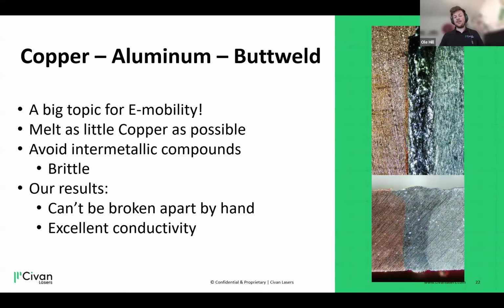We had a very successful run using a quite narrow beam shape, a small spiral, and we manipulated the workpiece in a way that we could get this basically vertical weld seam on the left side, which you see in the cross section, and the angled weld into the aluminum, which doesn't matter because you can melt as much aluminum as you want. It's maybe hard to see in this picture, but most of the interface in the copper is very slightly molten. It is not the case I described before, which is a brazing of aluminum. Just a few micrometers of copper are molten, and this results in a weld that is not so brittle.